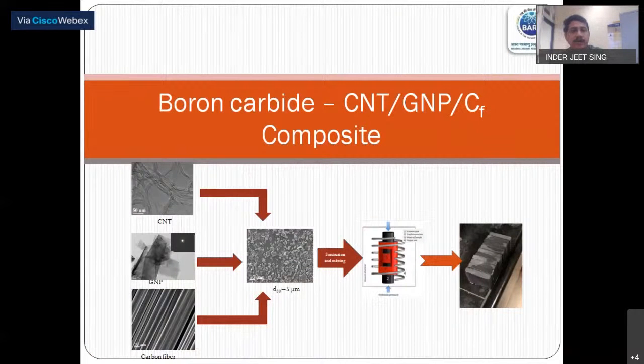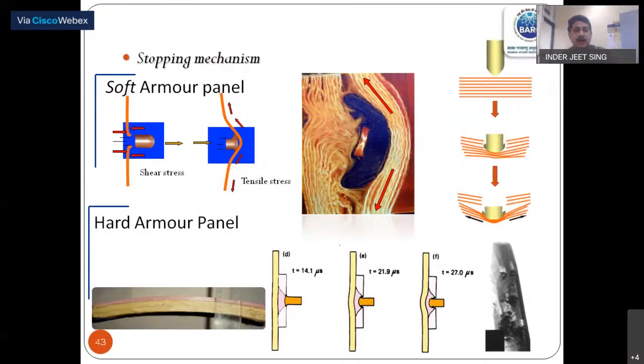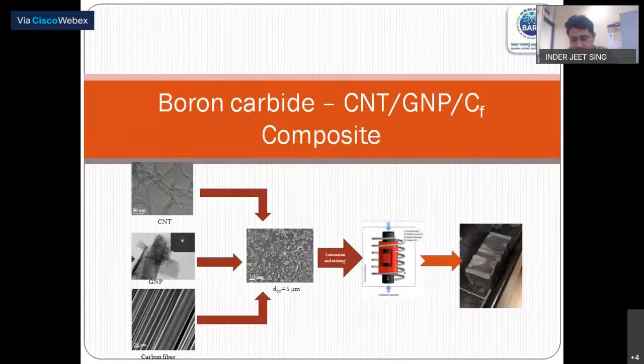Now I'll explain how we played with these hard armor panels. As I told just now, boron carbide is a very hard and light material, but it has a low fracture toughness, so it easily gets fractured. So what was our intention? How to improve the fracture toughness of boron carbide? We utilized different carbon materials: carbon nanotube, graphene nanoparticle, as well as carbon fiber. They were mixed properly, then hot pressed, and then we made tiles out of them.